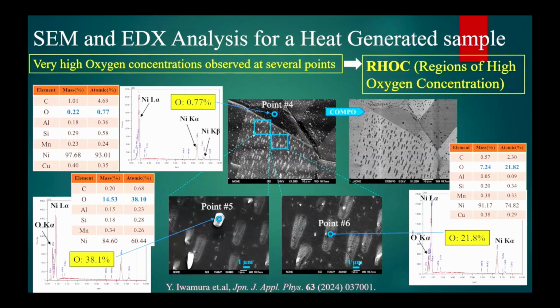And this is the experimental result so far: the data after the heat generation sample, SEM and EDX analysis data. We found a very high oxygen concentration region after the excess heat sample, like this. This black point corresponds to oxygen. If we look at this region, we cannot see much oxygen. But if we observe here and here, we detect very high oxygen like this. So we call these regions of high oxygen concentration, RHOC.